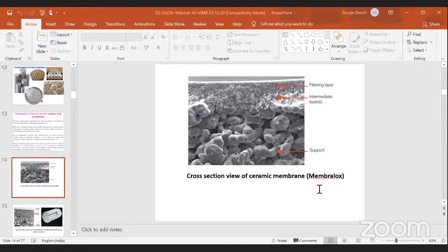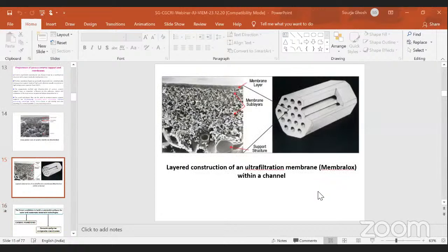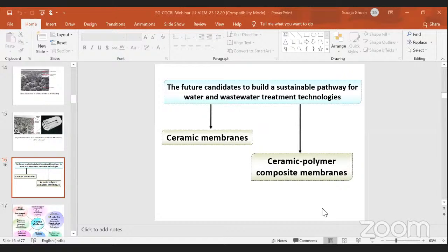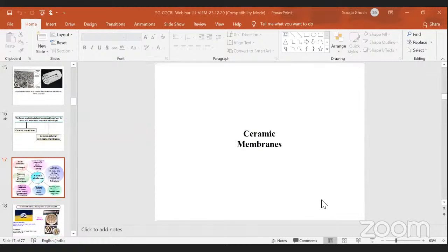So this is the typical microstructure of a ceramic membrane. You can see the asymmetric structure is very predominant. The lower part is the porous support, where the high pore size is shown. Over it, the filtration layer is given. Gradually, the pore sizes are reduced depending on the coating given on the membrane surface. This is another ultrafiltration membrane, in multi-channel configuration. Here also you can see the asymmetric pore structure arranged in a layered manner. The future candidates to build a sustainable pathway for water and wastewater treatment technologies are ceramic membranes and their counterpart, the ceramic polymer composite membranes, for a wide variety of water and wastewater treatment applications.